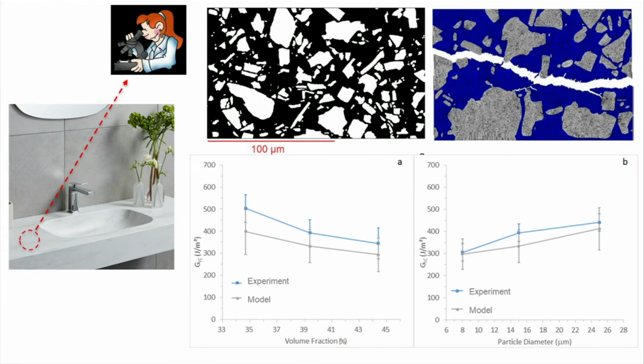And you can use models like this to predict important mechanical properties like the fracture toughness here, as a function of the amount, the volume fraction, of the particles you have, and the size of the particles. Once you make these models and you're confident that they're accurate, then you can use them as very cost-efficient design tools to make new composite materials.